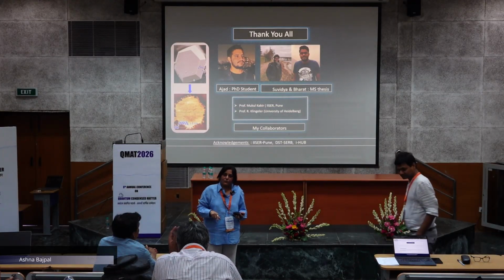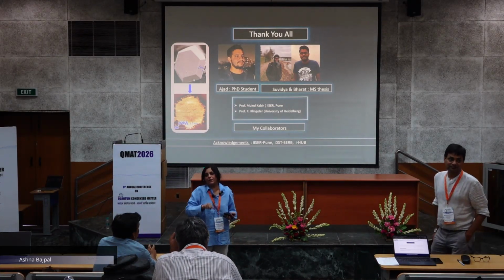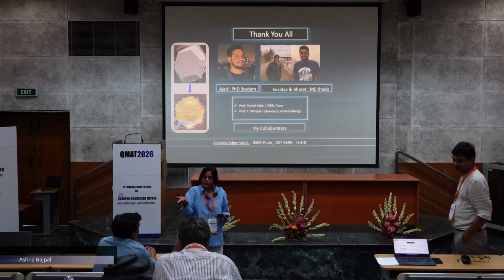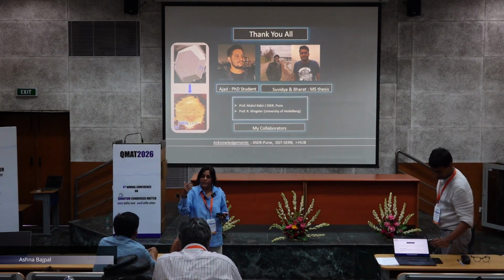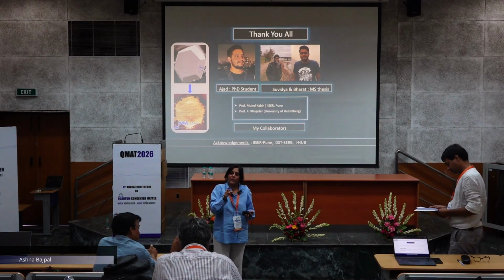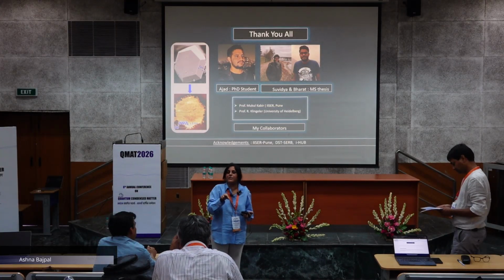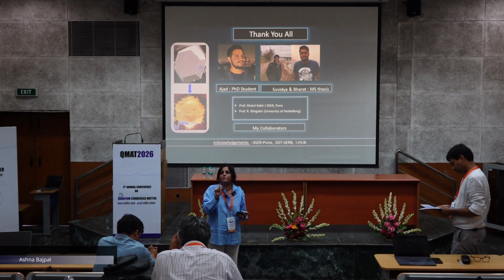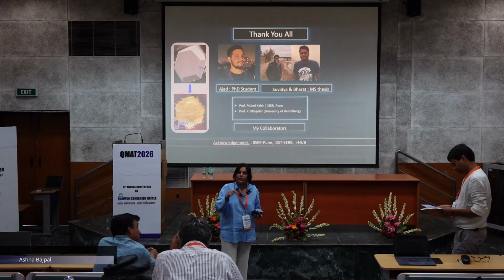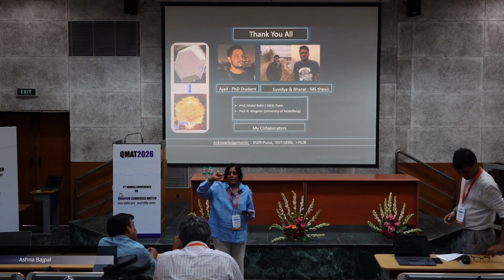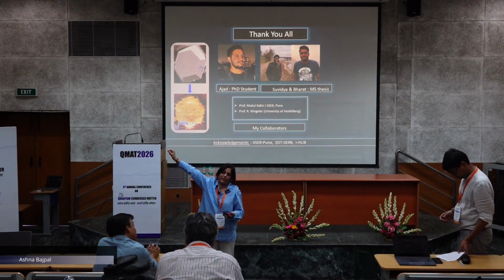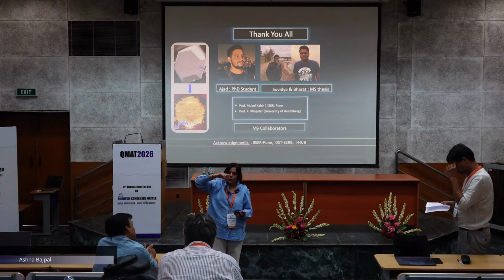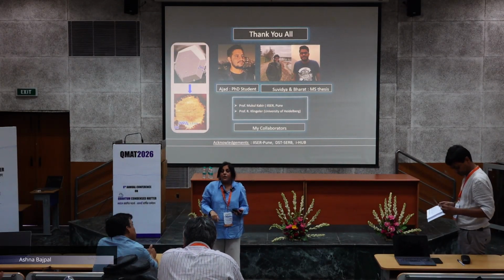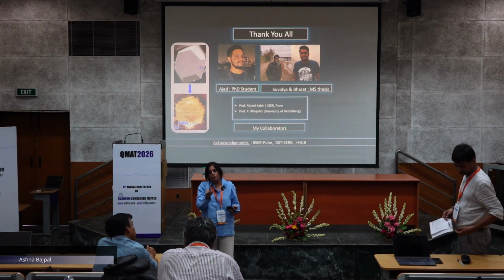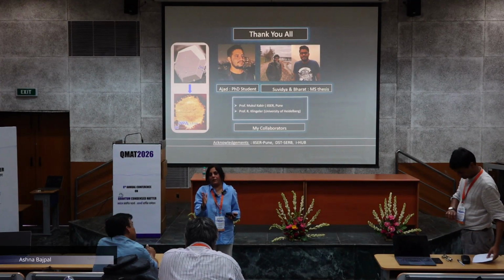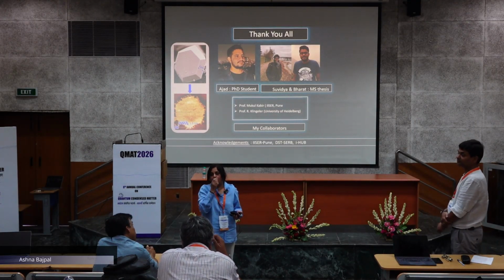Lithium would also lead to a change of valence, right? Yeah, so that is hole doped. We have done hole doped and electron doped with lithium and yttrium. With calcium itself, where the valence will not change, we saw a lot of change in magnetism. Basically this is an antiferromagnet, but a loop seems to be opening up, and still it remains an antiferromagnet. But the TN? In the calcium doped system we could do neutron diffraction, and TN remained the same even though a big loop opened.